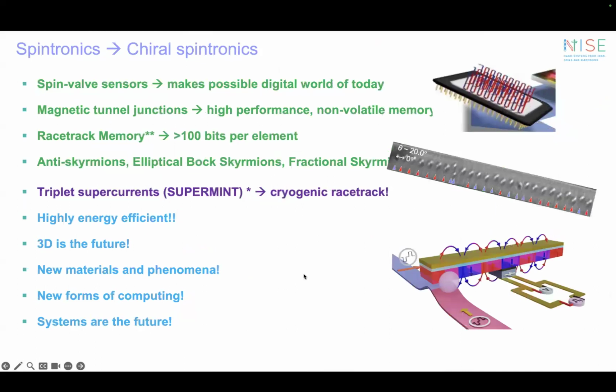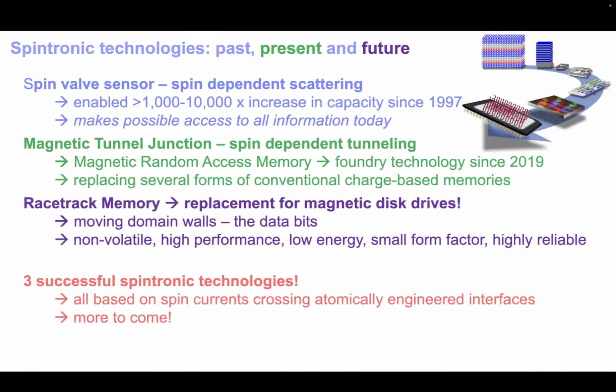So this is more of a transfer torque mechanism for driving domain walls in the same direction, regardless of whether it's from up to down or from down to up. Is there a good understanding of that, or is it still phenomenological mostly? No, there's a good understanding, and it's only possible when the domain walls have the same chirality. If they have opposite chiralities, then it's not possible. They would move in opposite directions.